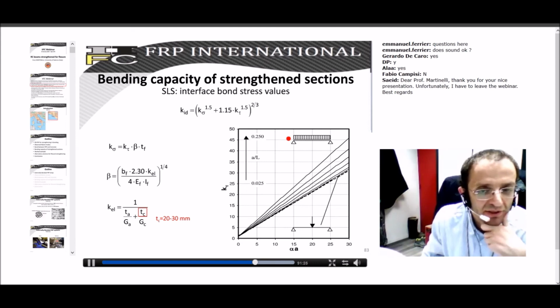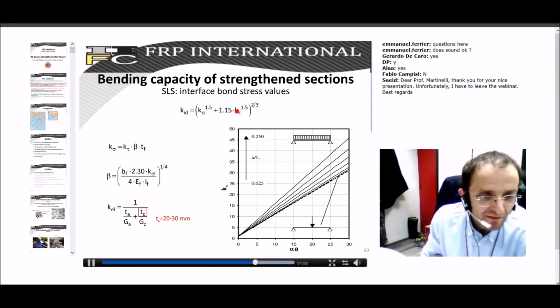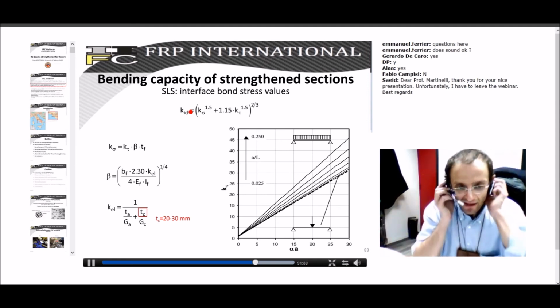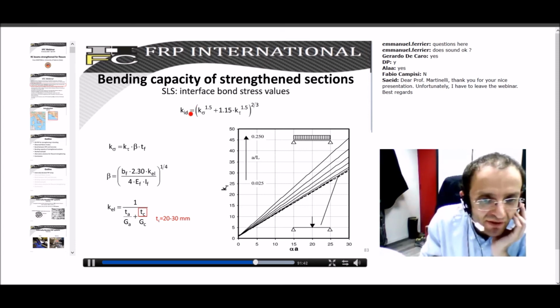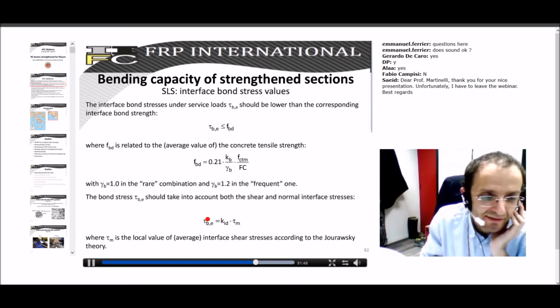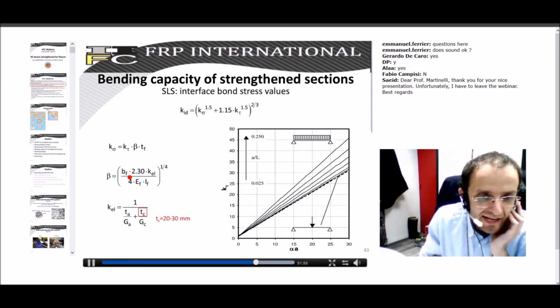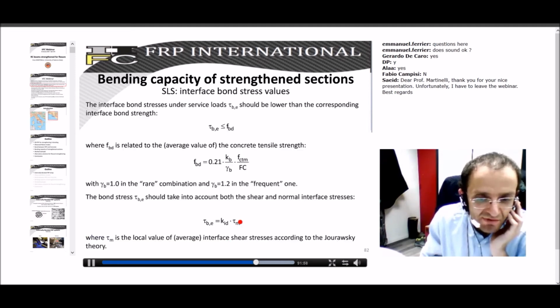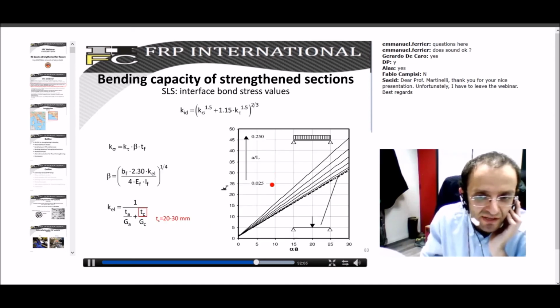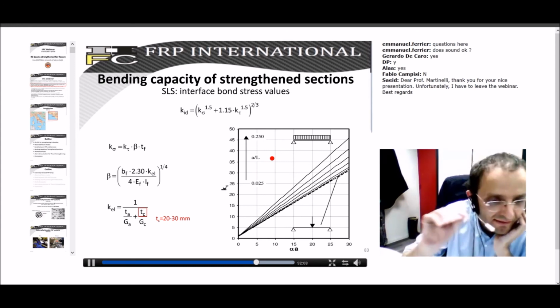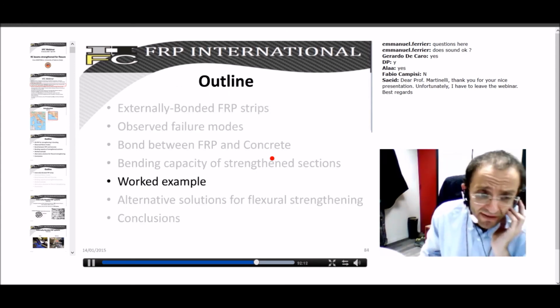theoretical support point. We can approximately take into account of the fact that we have not only interfacial shear stress, but we have also some so-called peeling stresses, some interface normal stresses, and then we can evaluate a modified KID to evaluate the resulting stress, taking into account the Jourawsky one. So KID is basically an amplification factor, which multiplies the Jourawsky values to take into account the cutoff section and the stiffness of the interface.